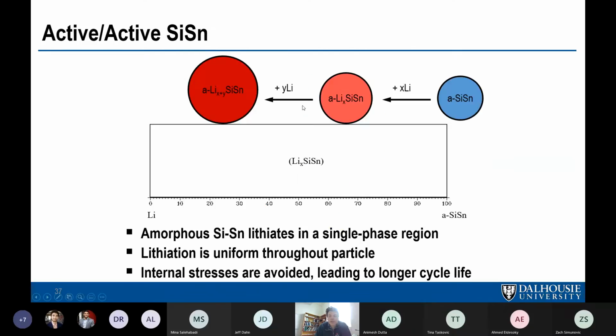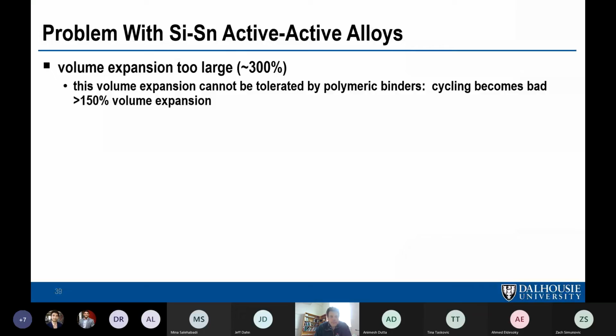It's often the case that you can lithiate a material in a single-phase region if it's amorphous, but there are rare cases that you can lithiate it and form a second phase, even if it is amorphous. So one thing to keep in mind. Here we go. So let me get my pointer back. Making things amorphous or nanocrystalline tends to make them lithiate in single-phase regions, and that reduces stress in the particle and gets you better cycling.